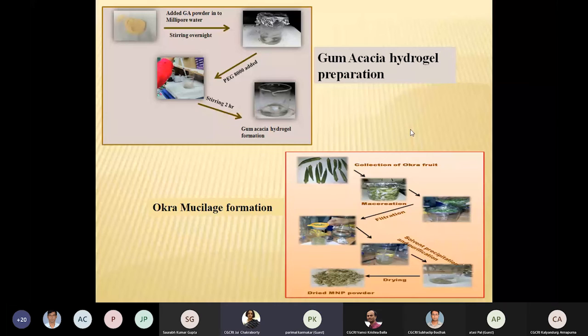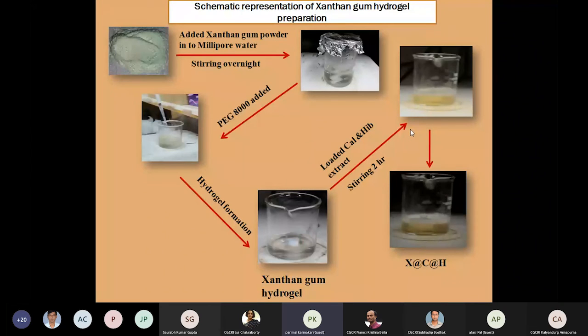But what we have successfully done, we use the xanthan gum hydrogel, and then this hydrogel is produced, and then they are loaded with two herbal excipients. One is calendula, another is hibiscus. So these are the two agents. First, we published a paper on their potency to heal wounds, and also for calendula we isolated the single component, and then that can be used.